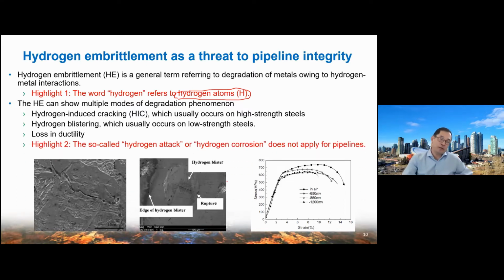Okay, highlight 2 in today's talk. In some literature and reports, a term we call hydrogen attack or hydrogen corrosion is also included in the degradation of metals. But I will emphasize that hydrogen attack or hydrogen corrosion does not apply to pipelines, because this phenomenon only happens for temperatures more than 250 degrees. So we don't worry if we use a pipeline to carry hydrogen. This problem will not happen.